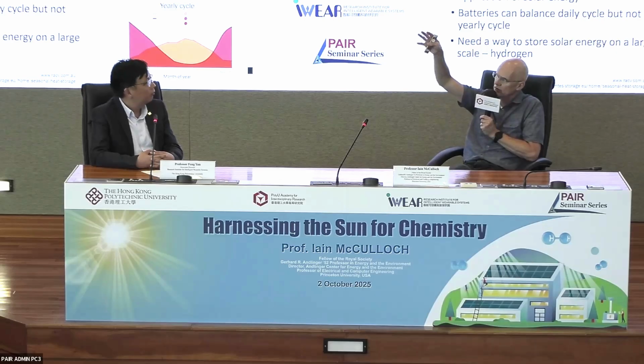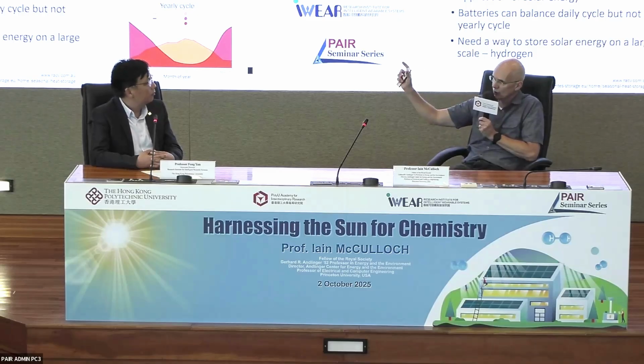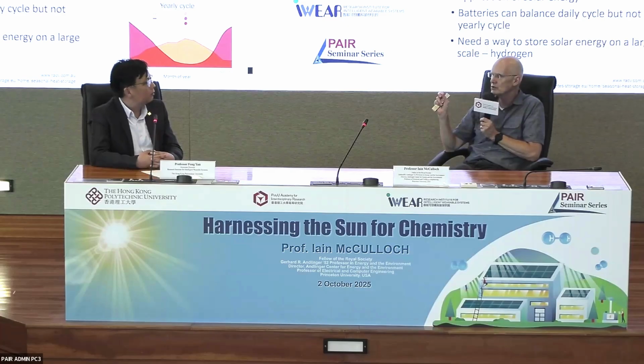Around 50 nanometers, you've got an opportunity for exciton splitting and free charges reaching the surface. So that's a good size. When it's too large, obviously in the center you get the dead zone: you split charges, but the diffusion length is not large enough to get to the surface. So we see this optimum size being around 50 nanometers or so. It's also very hard to stabilize very, very small particles.